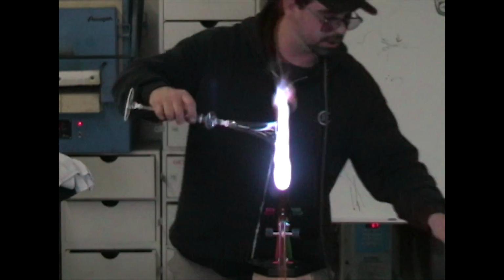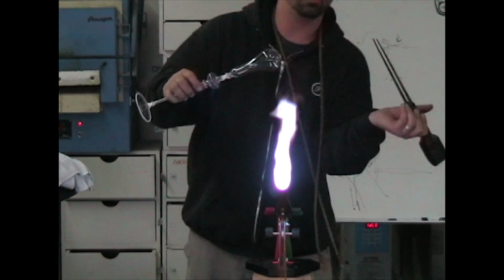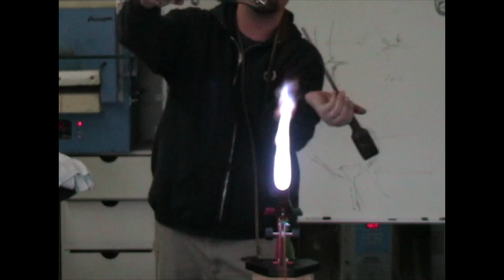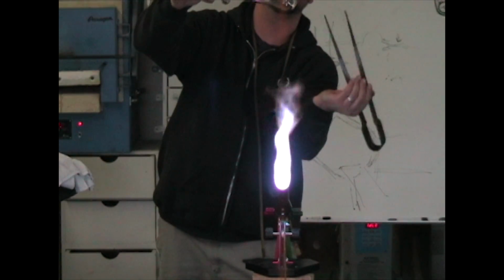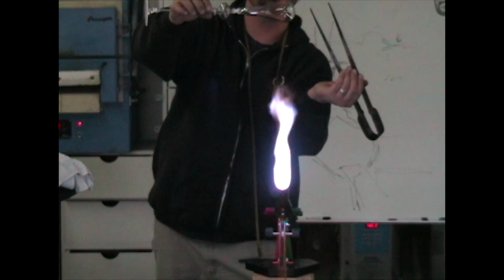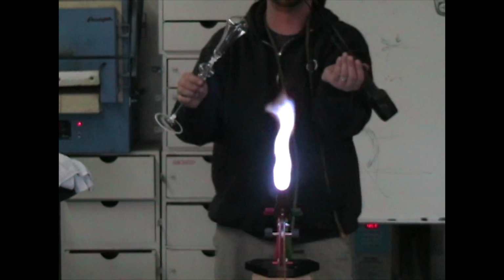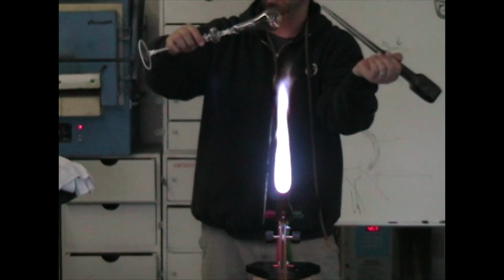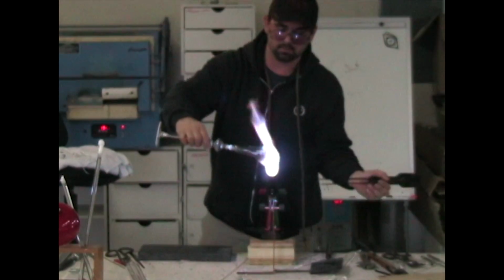And then I'm going to go in with my jacks and lift it out a little bit. I'm going to go in at the angle of the shoulder, at the angle the shoulder rolls down, so it'll be a very abrupt angle. The hole's small enough that I'll only go in with one jack blade to start, and I'll lift out. It's not really a prying motion, it's just a lifting motion, and I only put the jacks in as far as I need to lift it out. I don't try to stick them all the way in the back.